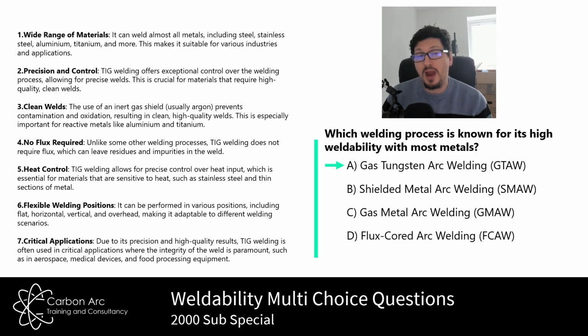So the amount of weld metal we produce per hour is tiny compared to the rest of the welding processes, and of course that's going to cause an issue when we look at cost. Okay, and it has a higher skill level compared to the other welding processes, so cost goes up again, skill and time. So efficiency is relatively low. Okay, but generally, when in doubt, TIG weld it, and you should be able to control the processes enough from a weldability issue to be able to weld a material.